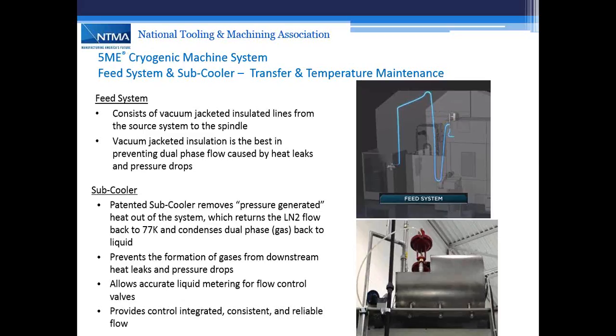What the subcooler does, it normally sits at the top of the machine tool. It takes the pressurized liquid nitrogen, and as we know from physics class, any liquid under pressure will gain heat. What we do is take that heat away by running a pressurized LN2 through a zero pressure liquid bath of LN2. And what that does, it eliminates the heat that's built up by pressure, but more importantly, we want 100% liquid, eliminating all the gas bubbles that would normally congregate into what's called a segmented flow in cryogenic flow. What normally happens with cryogenic gases or liquids, as they absorb heat, they start to create bubbles, they start to cluster together,